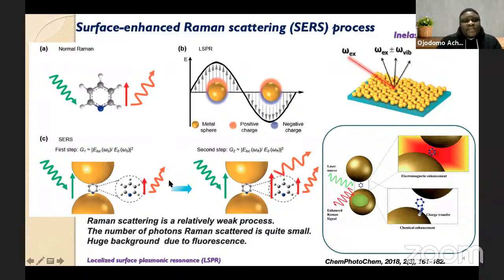But it has been observed that in the presence of materials such as gold and silver, this phenomenon was accidentally discovered, you can have this distinct Raman scattering be more enhanced and more intense. This is due to the phenomenon of localized surface plasmonic resonance that we see in noble metal nanostructures. So if you have a normal molecule, which would otherwise not give a significant or distinct Raman signal, caught up in between plasmonic nanomaterials, you can see quite significant enhancement in its Raman signal, which is the basis for SERS-based applications and processes.